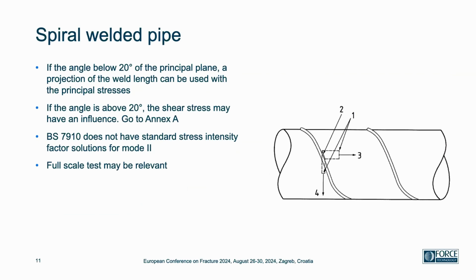Talking about the spiral welded pipe. In BS 7910, it's stated that if the angle is below 20 degrees from the principal plane, then you can use a projection of the weld flaw to either of the two principal directions. If the angle is above 20 degrees, then shear stress may have an effect on the results. And then it recommends you go to Annex A, which shows how you can combine different fracture modes, fracture mode 1, 2, and 3. The problem is that the standard does not have any standard stress intensity factor solution for mode 2 fracture. So in that case, we need to look elsewhere, either with finite element analysis or look at some of the comprehensive stress intensity factor solutions that are available in the literature.